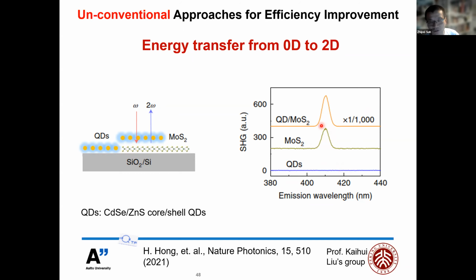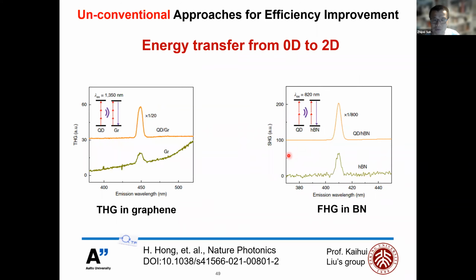To cut the story short, the physics behind this enhancement is that the quantum dots have a very strong multi-photon absorption coefficient. When the quantum dots absorb the light, they can quickly transfer the energy to the MoS2 for very efficient second harmonic generation. We also found the energy transfer process is quite universal. It also works with third harmonic generation inside graphene, and even for fourth harmonic generation inside boron nitride.